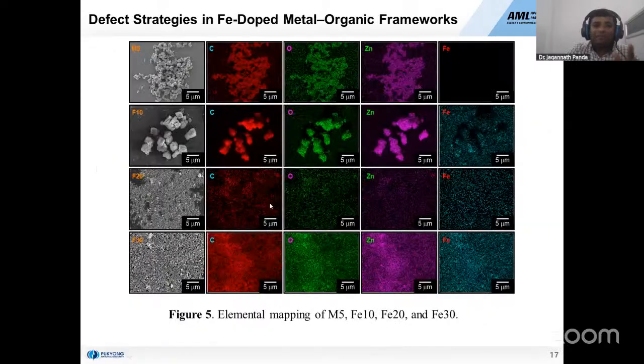Then we studied the EDAX spectra. There is a change in the elemental mapping. For each sample, we have carried out the elemental mapping. You can see here in M5 there is no iron present, but when you dope the MOF, it shows some iron present inside the MOFs.